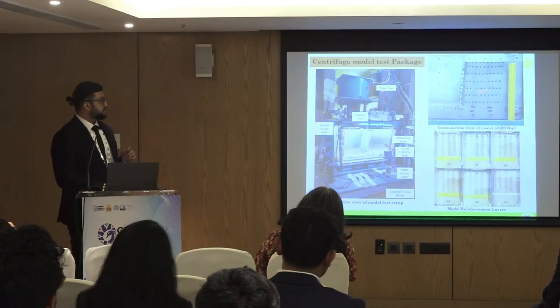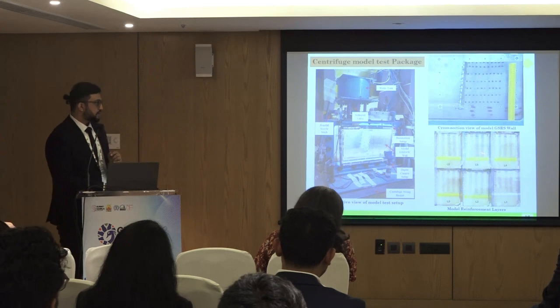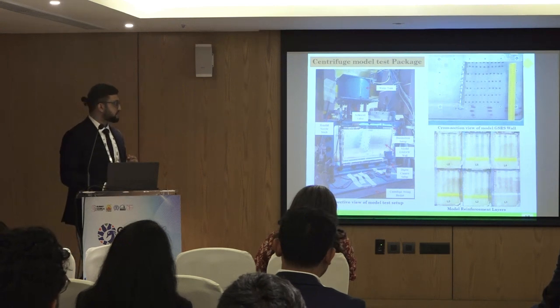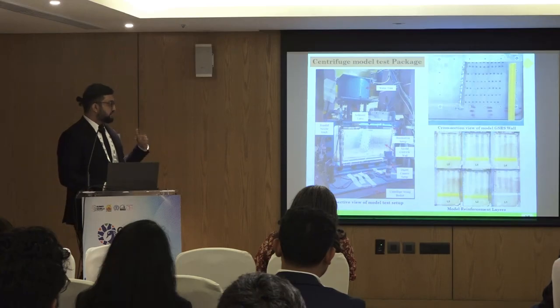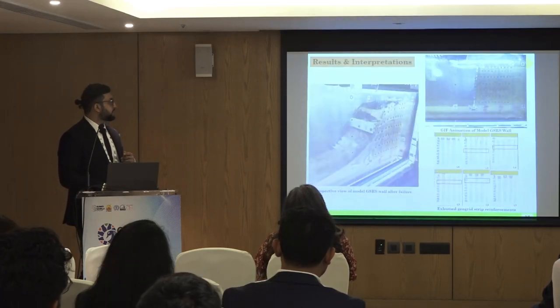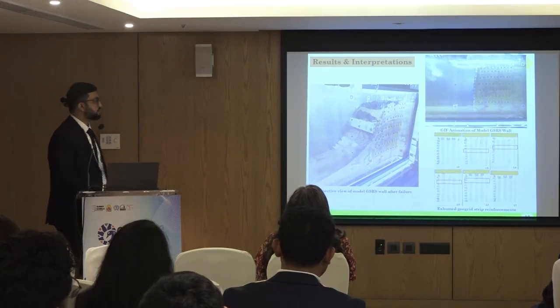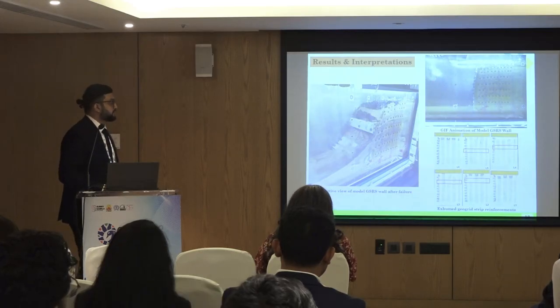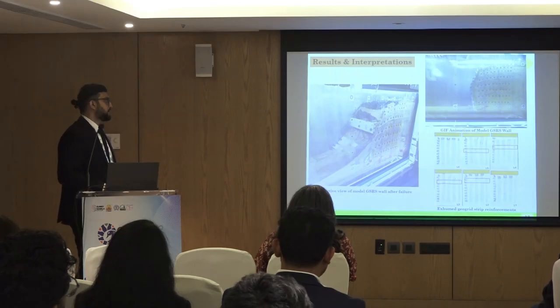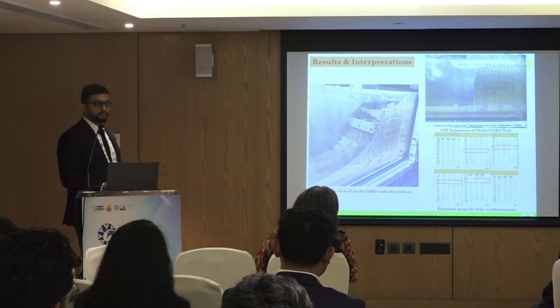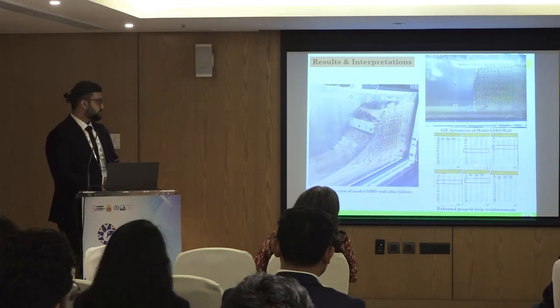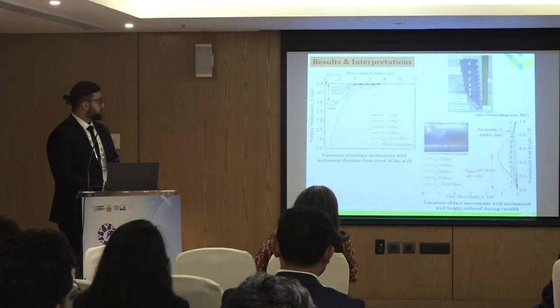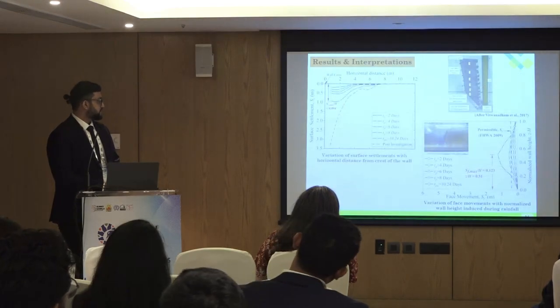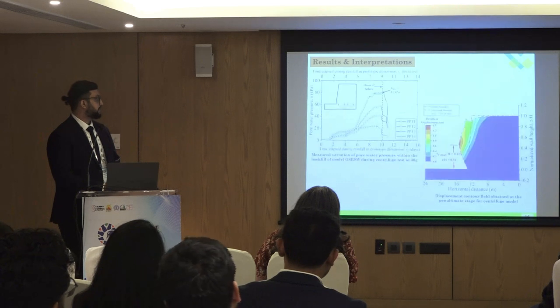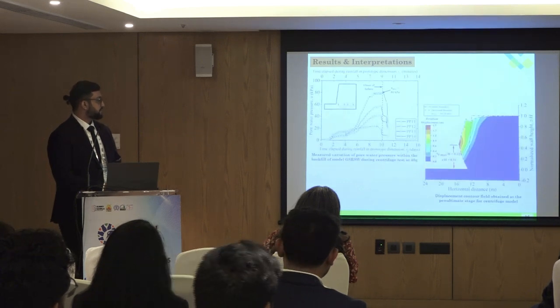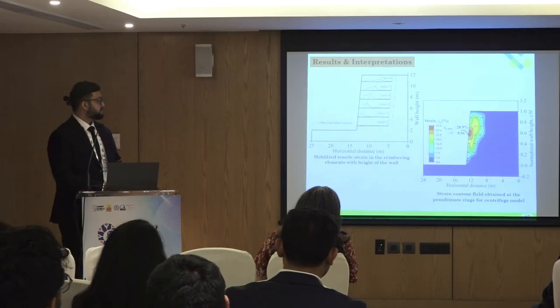I'll be showing that. This is the cross section, and this is the 6-layer reinforcement orientation that is placed in the model. This is before, while we are compacting the model. And here you can see the animation of all the GIFs collected. That's how it eventually failed at about 10 days. This is the exhumed geostrips. These are the deformations, some of the surface settlements and face movements that we have seen. Water pressure developments, displacement contours. These are the strain matrix.